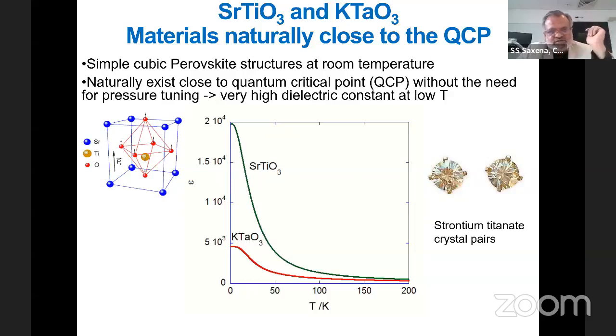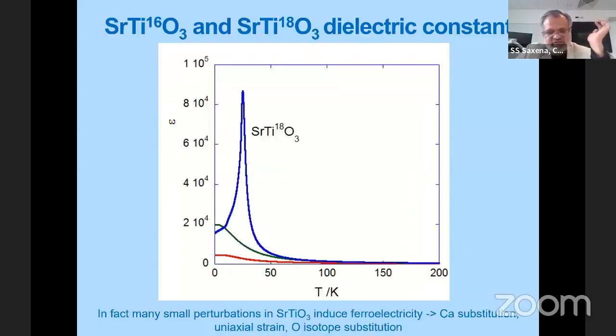And it's a cubic perovskite, but interestingly, it's something that we already understand lies near a quantum critical point, because if you perturb it, you do anything to it, you shine light on it, you squeeze it, you dope it, it immediately tends to become ferroelectric. So that means that it has been tuned naturally. It's sitting around that cusp. Let me also say that you can put in an isotope: instead of oxygen-16, which is normal strontium titanate, you put in oxygen-18, and it orders. That's your strontium titanate oxygen-18, which shows order around 30 Kelvin.